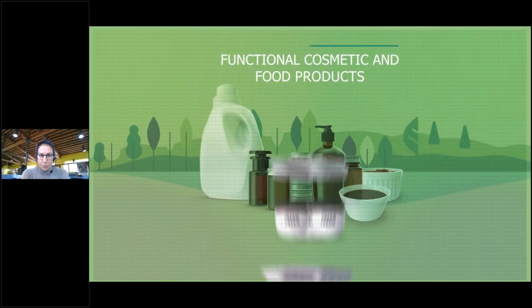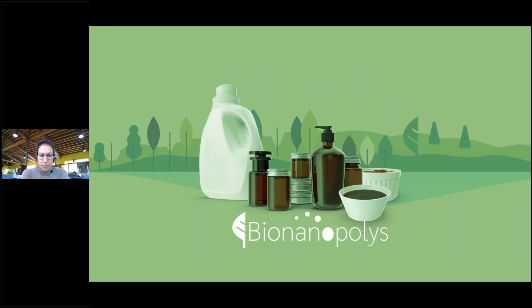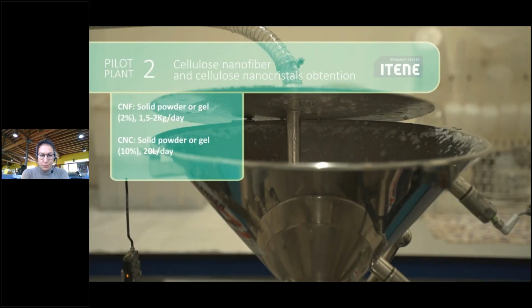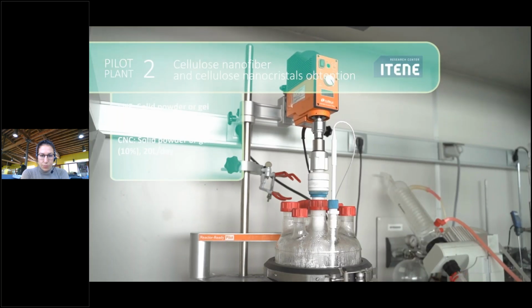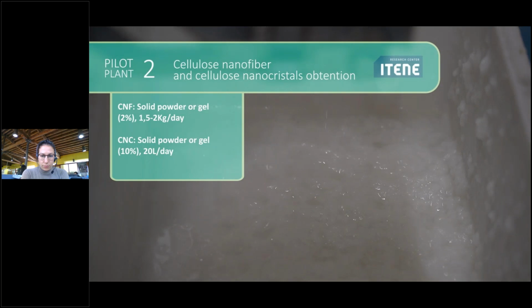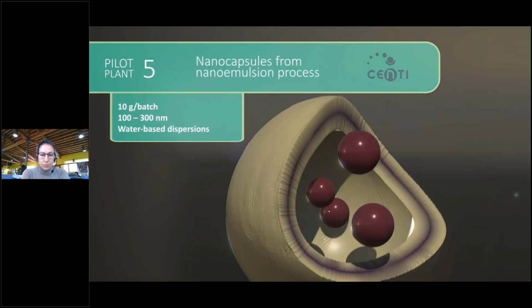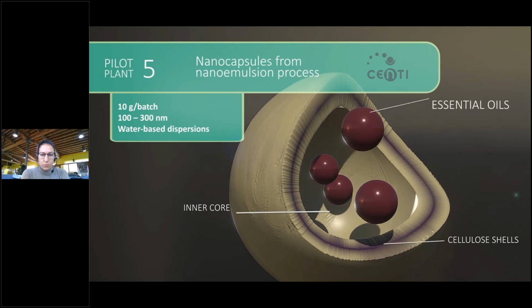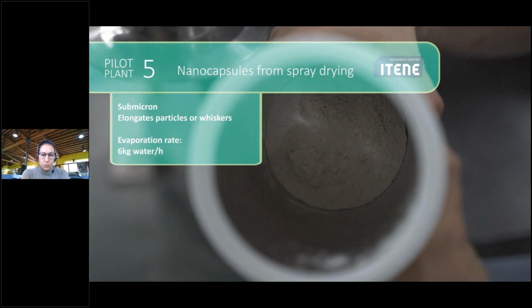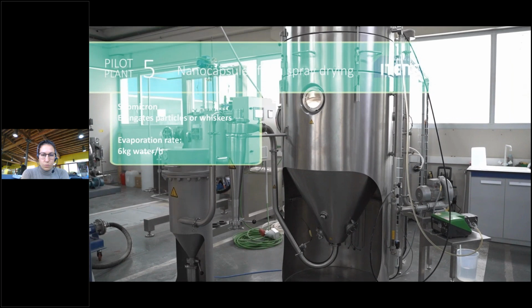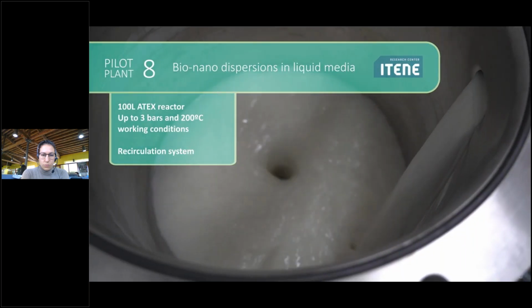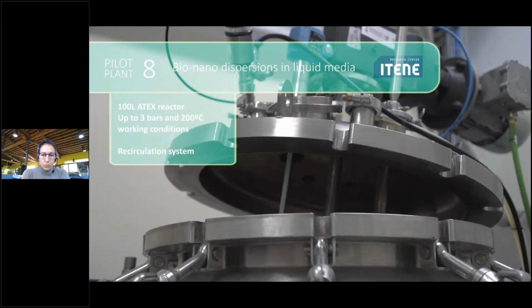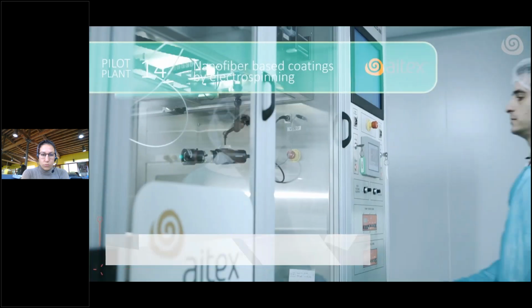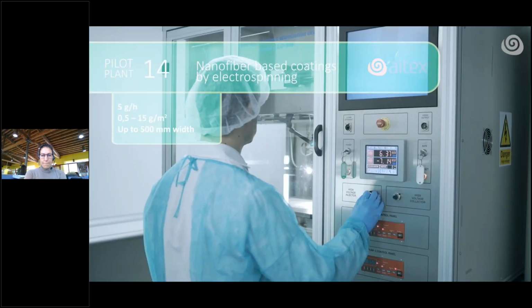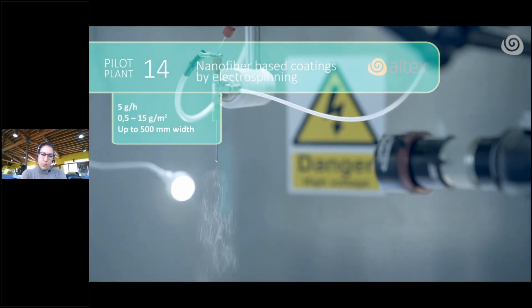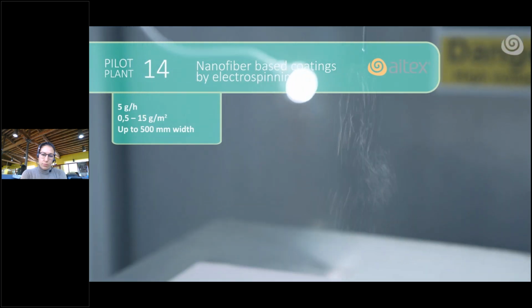For biofunctional cosmetic, food and detergent ingredients, Bionanopolis portfolio offers Pilot Plant 2 to produce cellulose nanofibers and cellulose nanocrystals used as film former ingredients. Pilot Plant 5 engineers cellulose shell nanocapsules functionalized with essential oils, which can be delivered in water-based dispersion or in powder form by using the Pilot Plant 5 spray drying system. Additionally, these bioadditives can be dispersed for coating applications using Pilot Plant 8 bio-nano dispersions in liquid media. Nanofiber-based coatings can also be developed through Pilot Plant 14 electrospinning, being an approach to encapsulate additives into nanofiber web for controlled release.